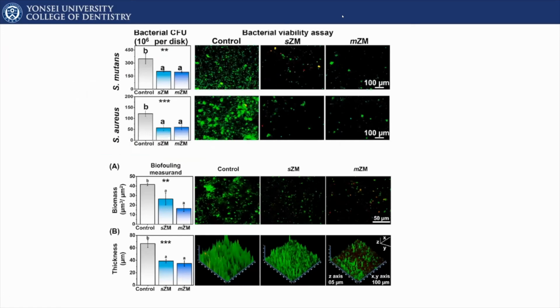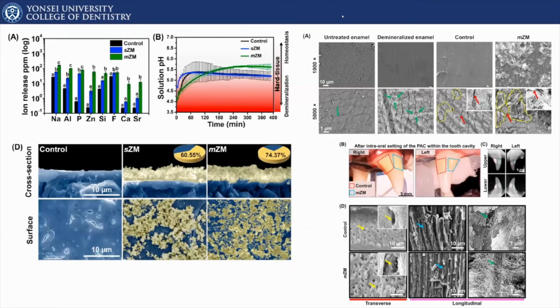So in terms of the addition of bacteria, it is as expected. No matter what kind of zwitterionic materials we have, there is a significant reduction of bacterial attachment. This, mind you, is a very new glass ionomer material with a performance that has been stated to be antibacterial, so it's even greater than zinc-containing glass ionomer in terms of the prevention of bacterial attachment and perhaps killing of these bacteria. And in terms of the oral biofilm, the effects were also what we expected. There's a dramatic reduction of the oral biofilm formation and attachment on this surface, although you may say the layers are much thinner with these multiple ZM materials. But effects were much more dramatic when we consider ion release and bioactivity related to regenerative effects.